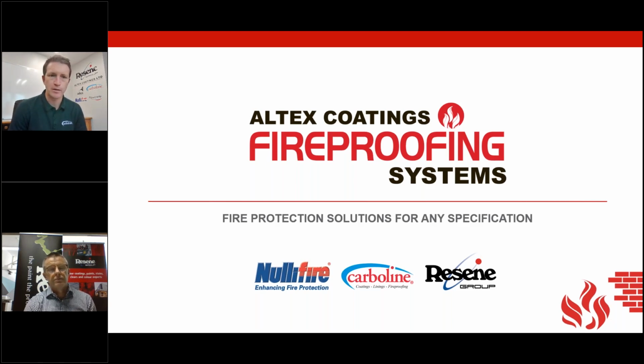Anything that's a bit more protected, that's where you can choose to use the likes of your waterbornes, if it's fully encapsulated from any sort of moisture contact. But if you're more open, that's when your FX and your ProSeal come into play. Anything that's put into the building that's been made watertight, or where there's no chance of water getting onto it, for example underground car parks, is an absolute sitter for the Southwest Type 5 material, a vermiculite material. The cost savings of those different splits, particularly using those cementitious materials, is huge. The cost difference between those materials and your liquid applied materials is rather large, especially for larger buildings, and they can offer some pretty significant savings.